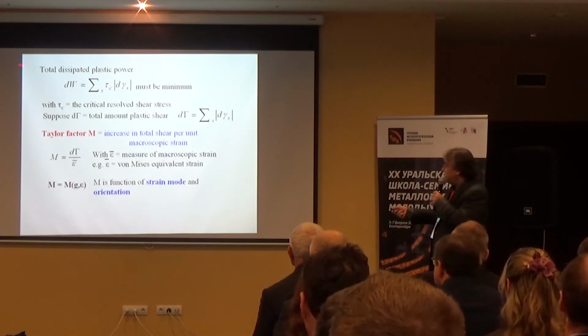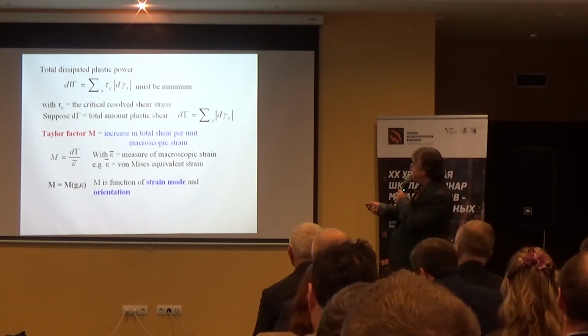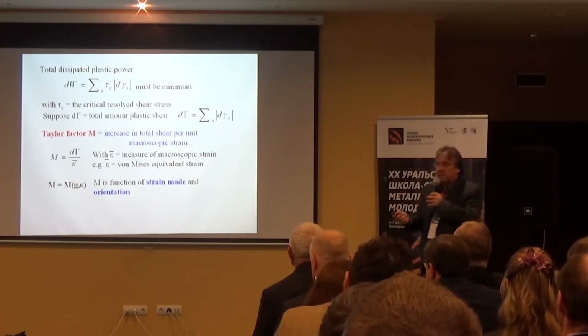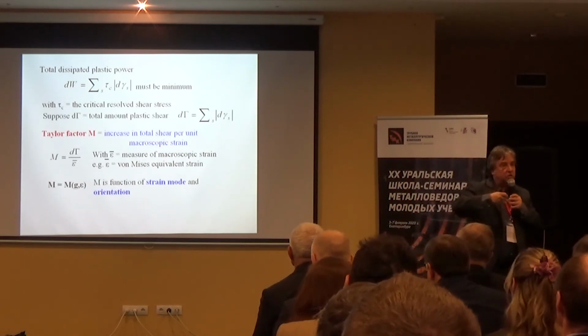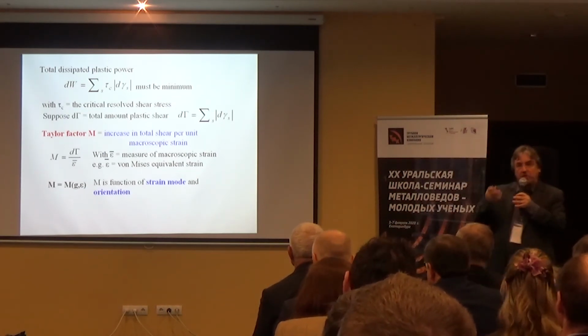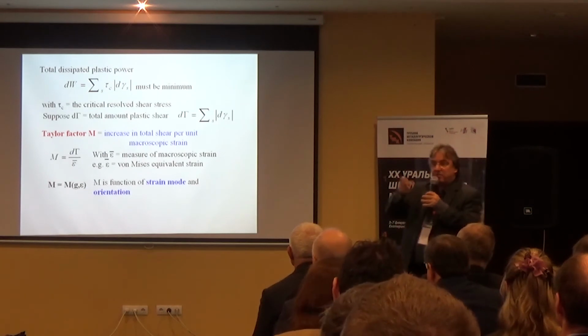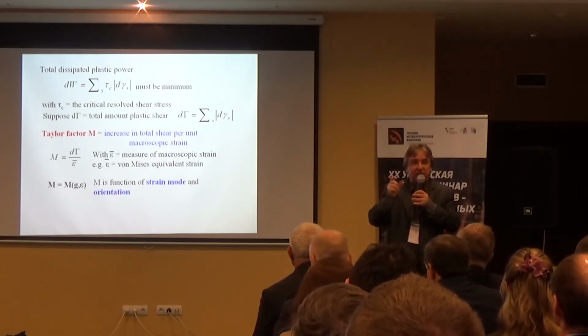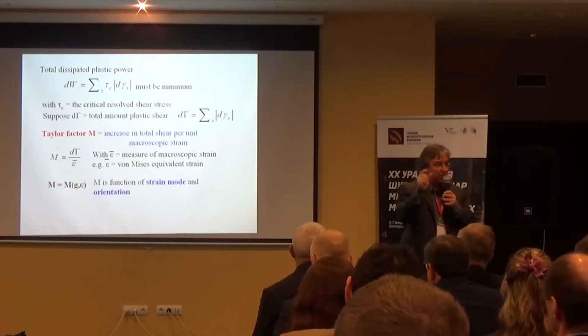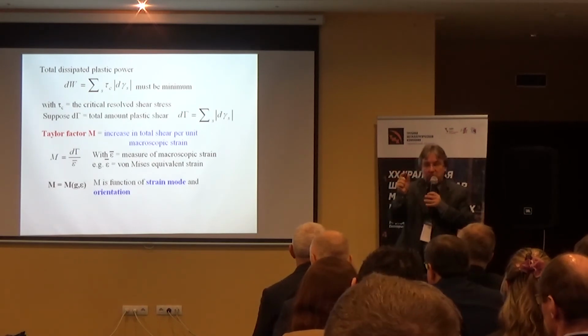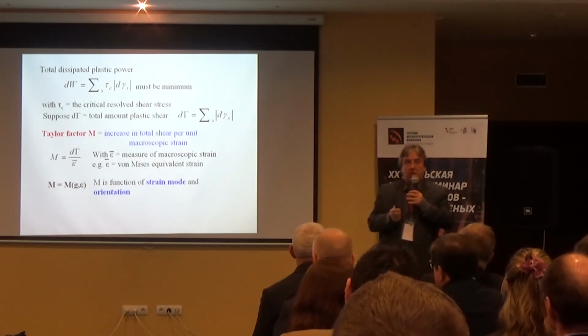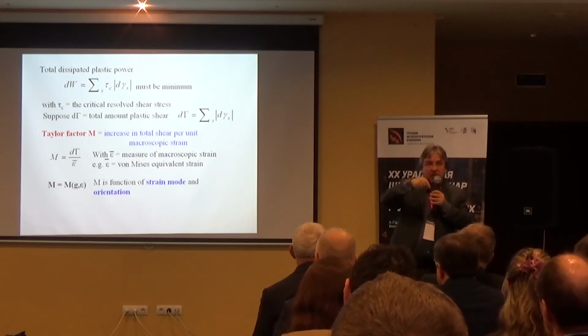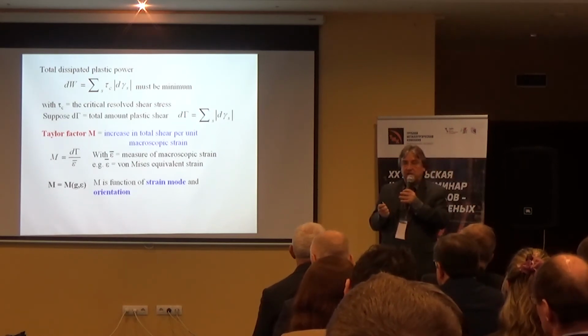Very important is the total dissipated plastic power. This is the energy that is dissipated during strain. The largest fraction of this energy is dissipated as heat, but a certain fraction, 5–10%, will be stored in the material as residual dislocations.